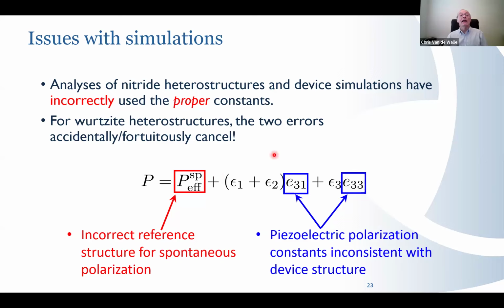Okay, so coming back to the full expression for the polarization, there is a spontaneous polarization contribution, there is a piezoelectric contribution. We have been using an incorrect reference for the spontaneous polarization, which actually leads to a large error. But we've also been using incorrect piezoelectric polarization constants, which accidentally, that second error has largely canceled the first error. And hence the calculated values are not obviously all that different from the experimental values. Now, in my opinion, the fact that you make two errors doesn't make things okay. I would really prefer us to do things correctly.